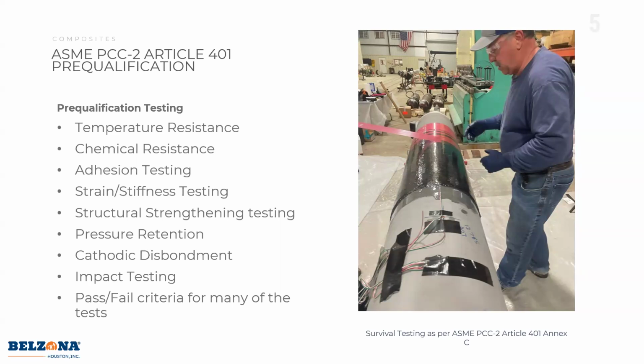But the epoxy resin is going to give you your temperature resistance, your chemical resistance, and your adhesion. All that is very dependent upon your resin. So you have to do a lot of testing to make sure the resin's not going to go soft at a certain temperature. It's not going to get eaten up by certain chemicals, and it's going to stick to the substrate good enough so that it doesn't come off.